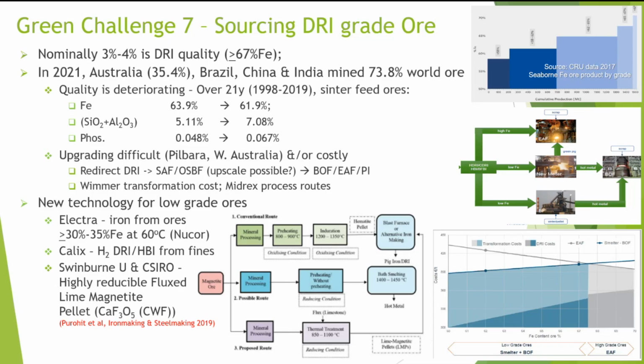There's new technology for the lower grade ores. Electra is producing iron from 30 to 35% iron containing ores at 60 degrees centigrade, and that's being sponsored by Nucor. There's a process out of Australia I'll go into a little bit more later, which is producing DRI with hydrogen from fines. And Swinburne University in Australia, along with CSIRO, are working on this highly reducible flux lime magnetite pellet, and that's allowing the process to be basically constrained a little bit, and two process steps are being removed.